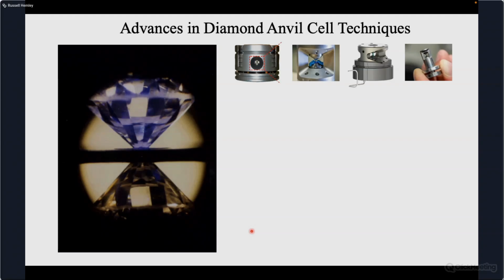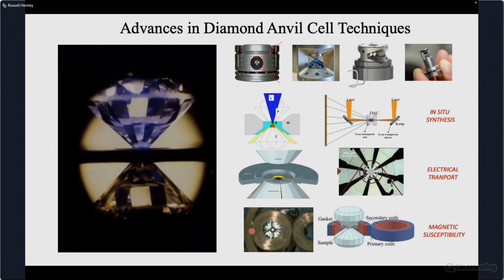A very important aspect of this is the technical side, that we now are able to do a lot of different kinds of measurements, not, of course, the number of measurements that we can do under ambient pressures, but we can do in situ synthesis with laser heating or various other kinds of heating. We can measure electrical transport by building circuits inside the diamond anvil cell. And we can also measure magnetic properties, such as magnetic susceptibility, by putting coils around our samples or putting our entire diamond anvil cell into very large magnets at large facilities.